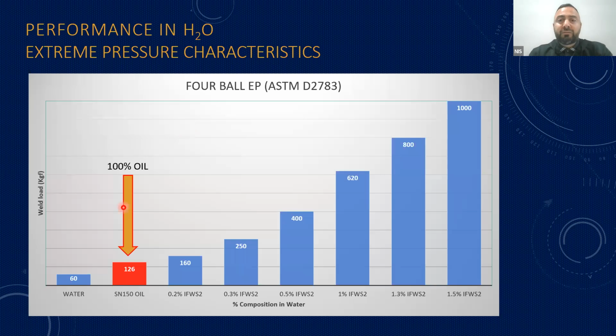So now we're going to compare 100% oil with almost 100% water with some of the material particles. This test, called 4-ball EP, is a standard ASTM test that measures the strength of the lubricating film. I'm sorry, not the film thickness, but the strength of the lubricating film. It measures in kilogram forces. So the more kilograms the lubricating film can withstand, the better this lubricant is, specifically for demanding applications like gears and many others. Okay, water is not a lubricant, of course, so that's a small number. We don't even know what the number is, but we just put 60 because we cannot measure below that. It doesn't withstand any load.